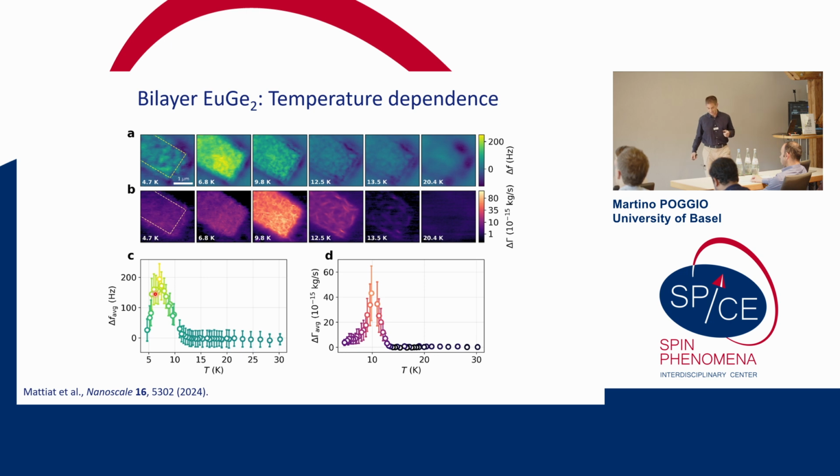And it turns out what's happening here is actually we're making measurements not of the stray field, but actually of the local magnetic susceptibility. So you can imagine that this magnetic tip, it's actually producing a relatively large stray magnetic field on the order of 10 millitesla or so, and as it's oscillating above the sample, it's changing the local field at the sample underneath. And the magnetization of the sample is responding in some way, in some parts in phase, in some parts out of phase, and this then acts back on the cantilever. So it turns out that this signal here in the frequency shift is proportional to something like chi prime, the in-phase susceptibility, and this one is like chi double prime, the out of phase susceptibility.